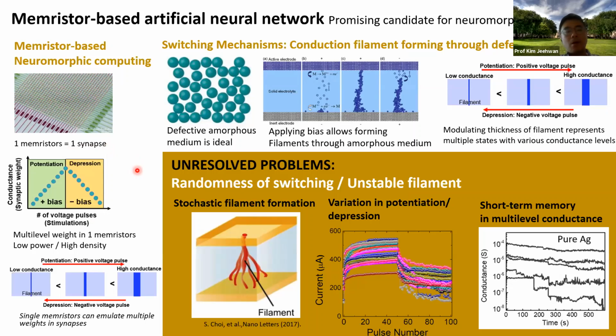So let's discuss the switching mechanisms in the memristor device. To do so, we need some understanding of materials. Typically, people have been using an amorphous material as a switching medium. In amorphous material, there are tons of defects, especially vacancies. Through these vacancies, we can send positive or negative ions. In this example, I have drawn the positive ion movement through the defects in the amorphous switching medium. This amorphous switching medium is also called a solid electrolyte. So through the defects in the solid electrolyte, you can send metal ions through.